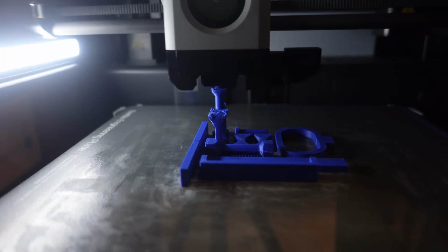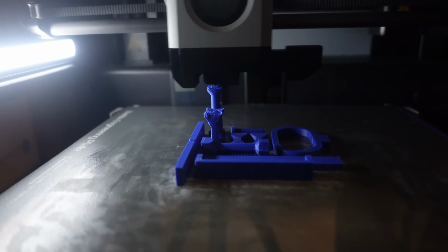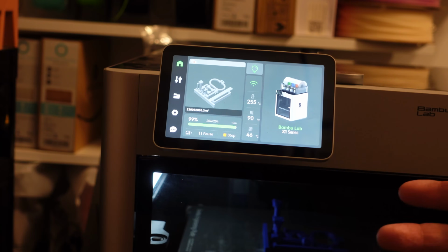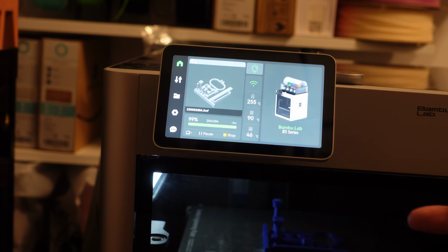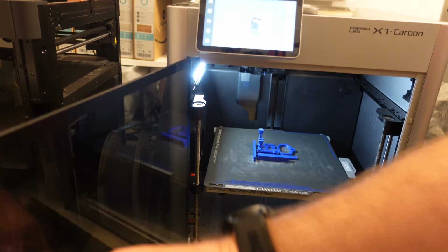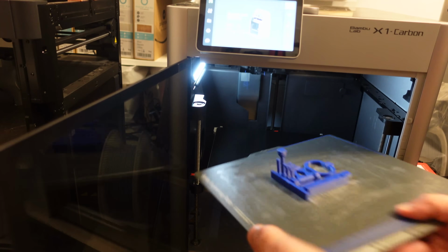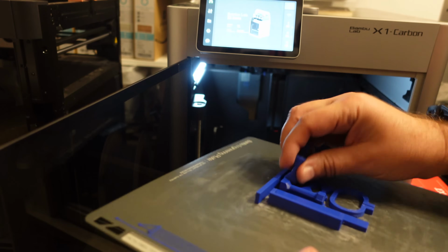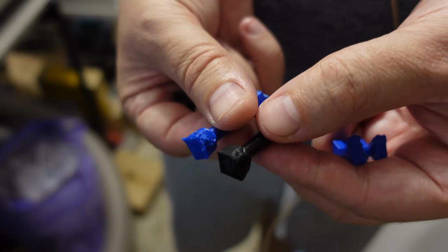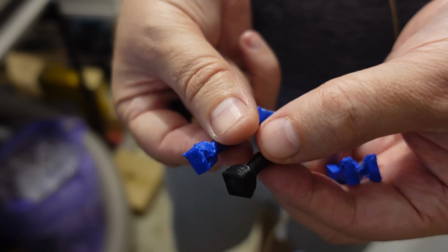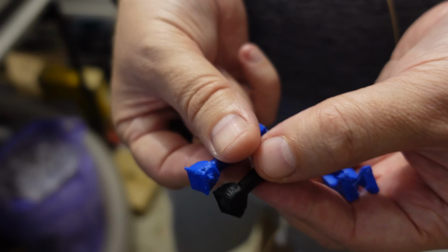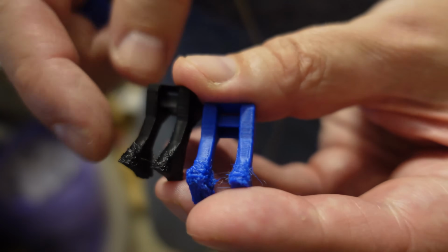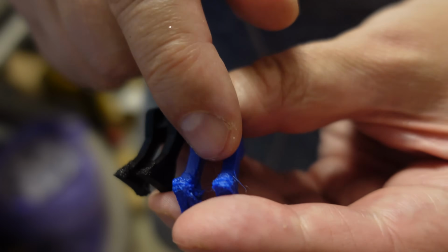I don't really like these big overhangs, probably I have to reprint a few objects. The chamber temperature inside is 46 degrees Celsius, which is not much, and the printing is finished. The bed already cooled down, let's check the objects. They are straight, no warping, only I don't like this overhang here. Maybe we found the first advantage of the ABS, is it maybe easier for the printing? So this is that critical overhang. These are not perfect, but way better than the ASA.